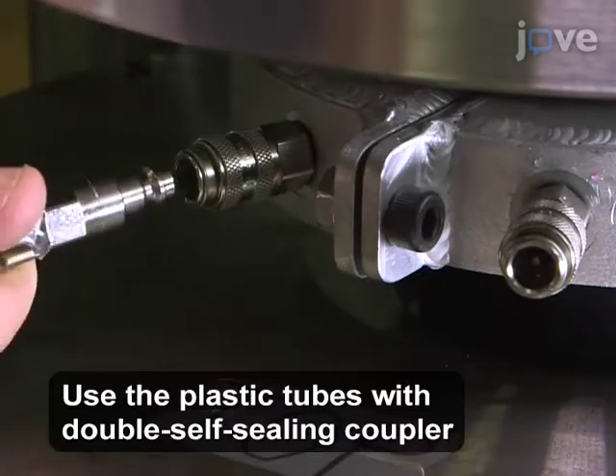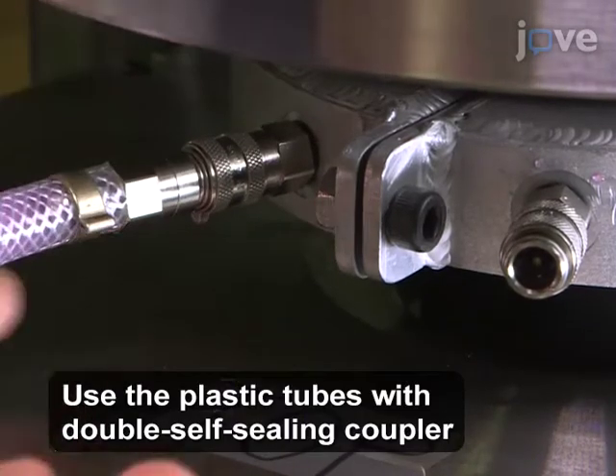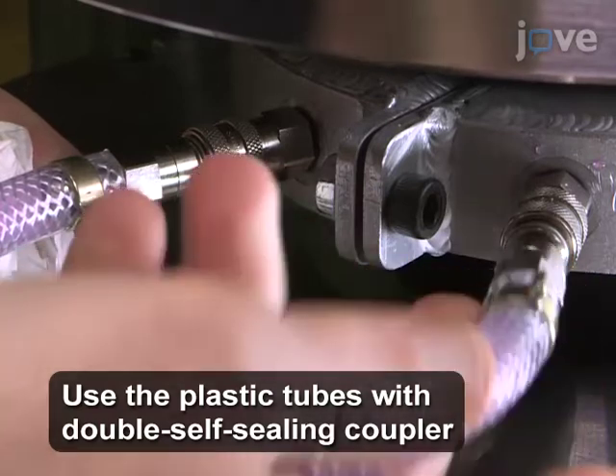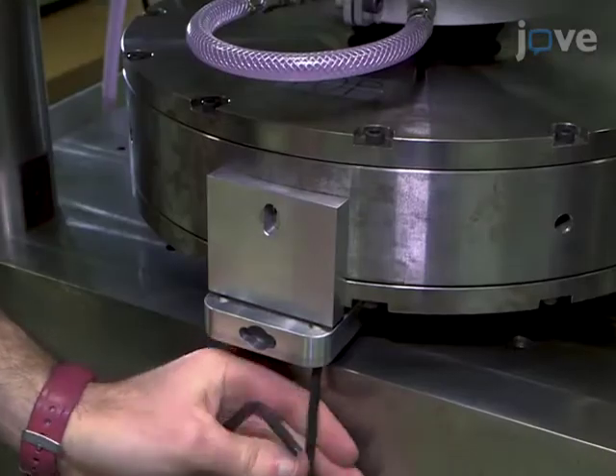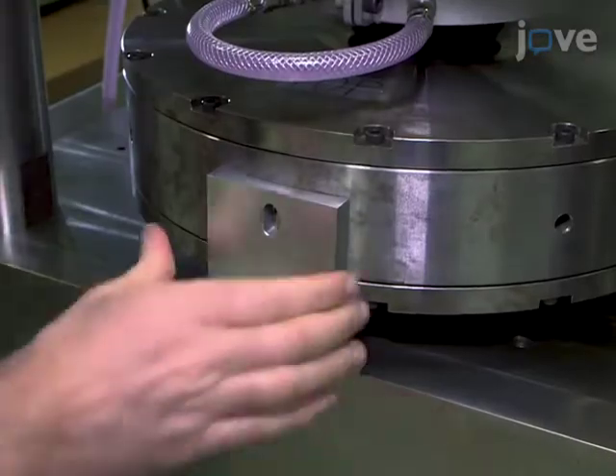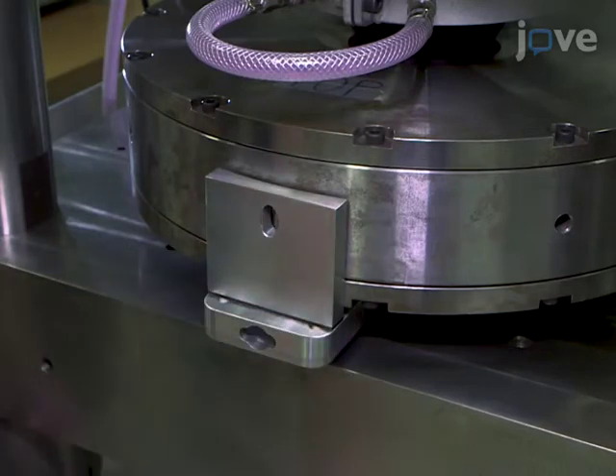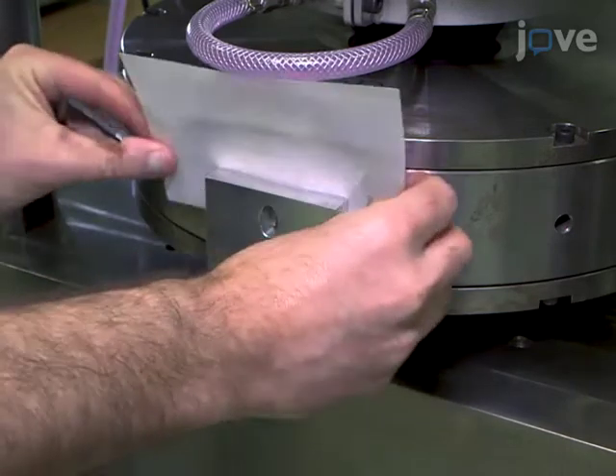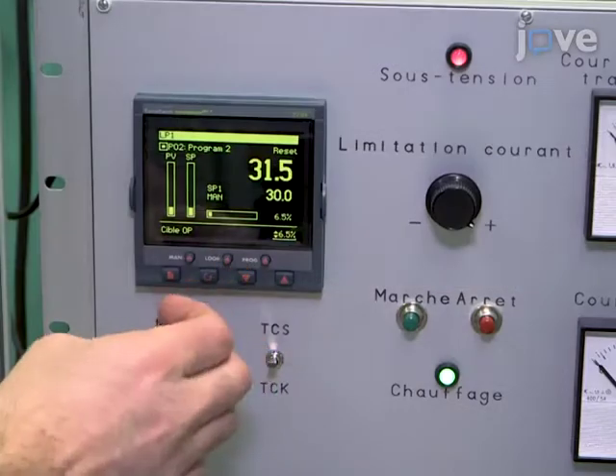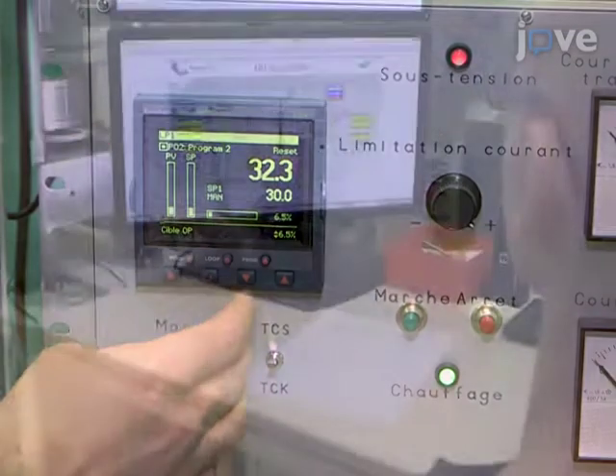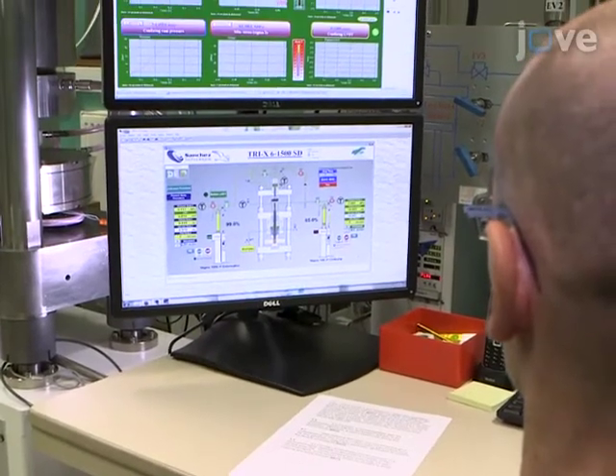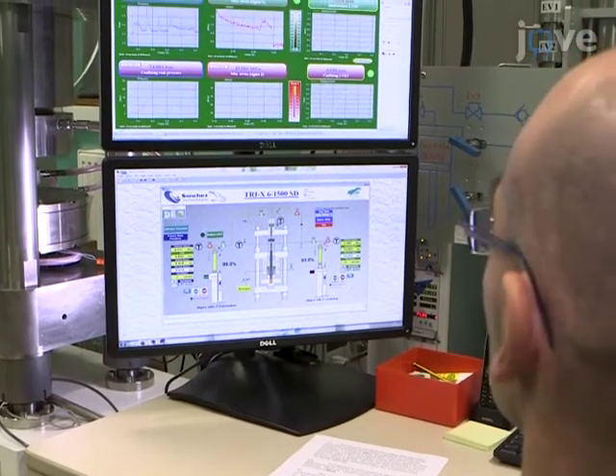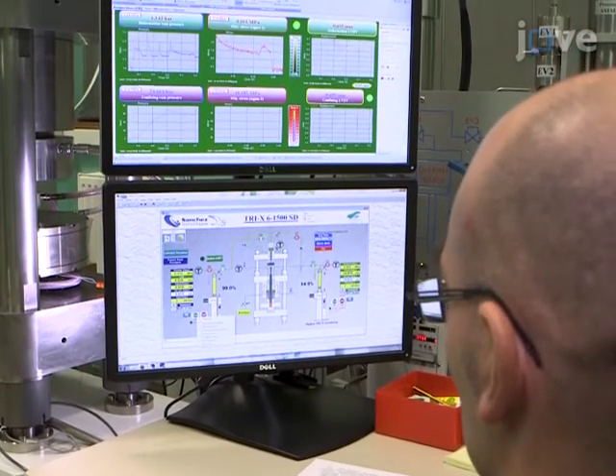When the confining pressure is around 50 megapascals, plug the vessel and pistons to the cooling system, and detach the upper part of each clamp that fix the base plate to the pressure vessel. Add a foil of mylar film between the clamps and vessel, and start heating as described in the text protocol. Then, use the hydraulic pumps, heating system, and cooling systems to perform the deformation experiment.